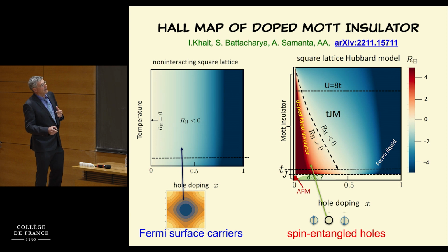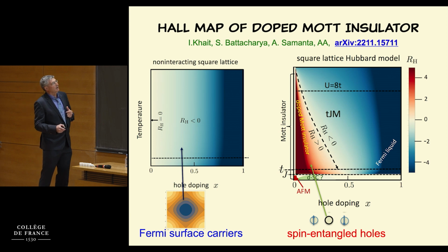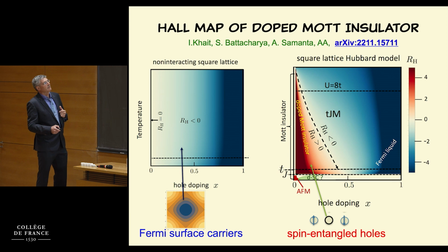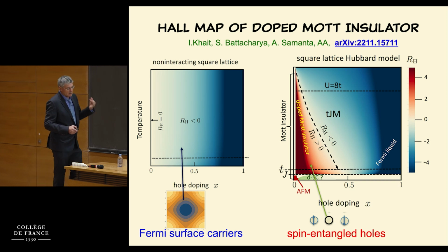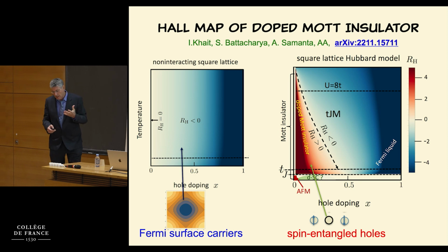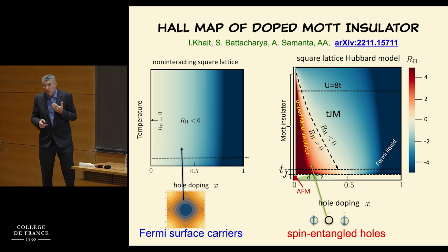So I'm talking about high temperatures relative to the hopping rate and also relative to any kind of magnetic exchange and maybe superconductivity at low temperatures. And in this regime here, you get a very different behavior. So you get this anomalous behavior I described that was observed experimentally, but it has far-reaching implications about how we understand the low-temperature physics.